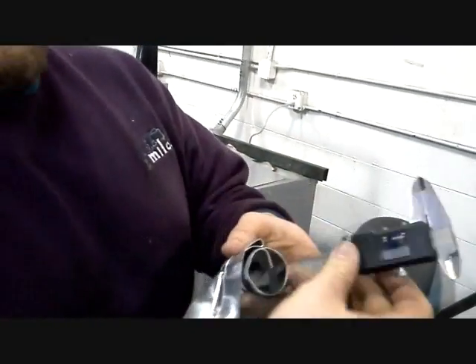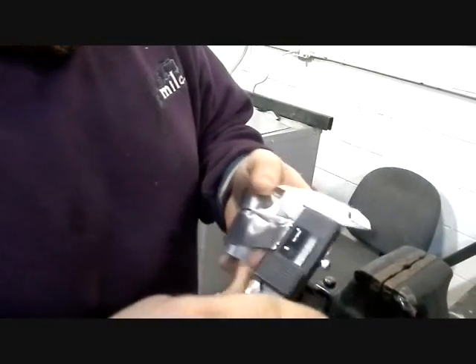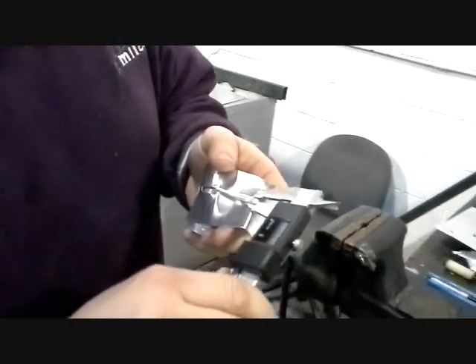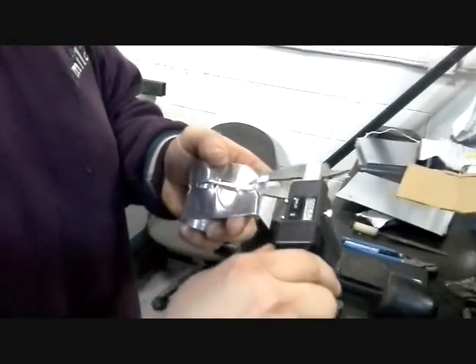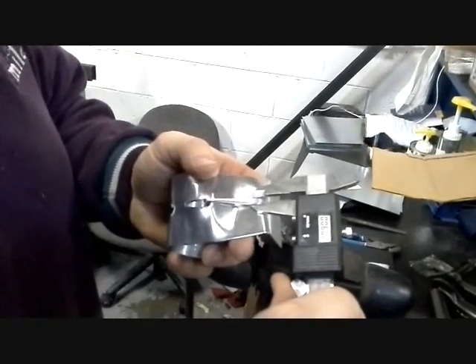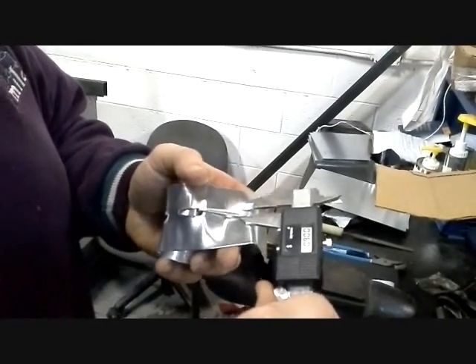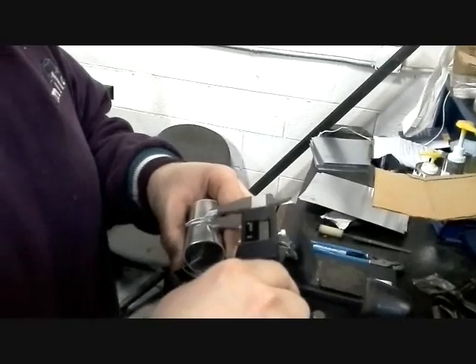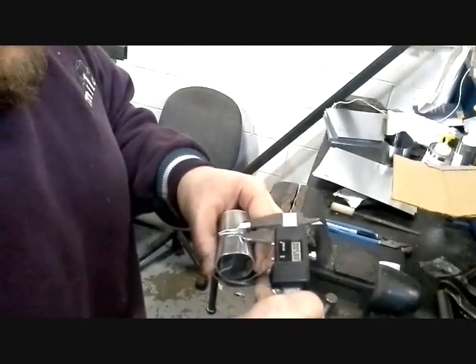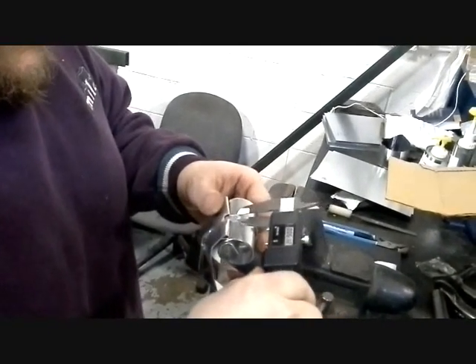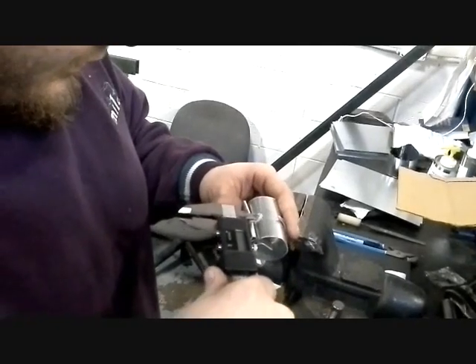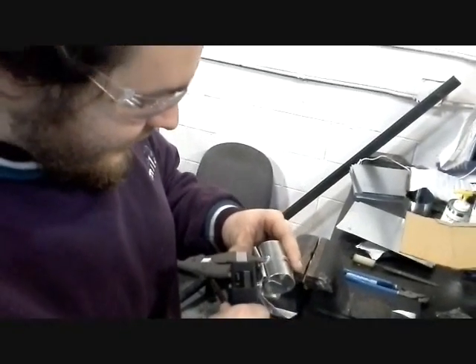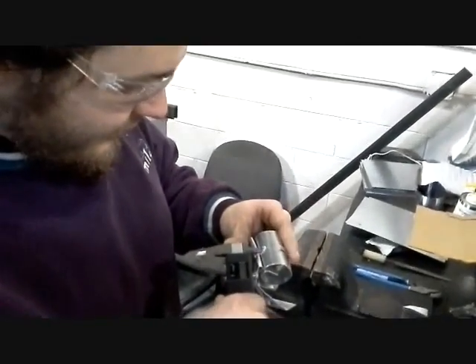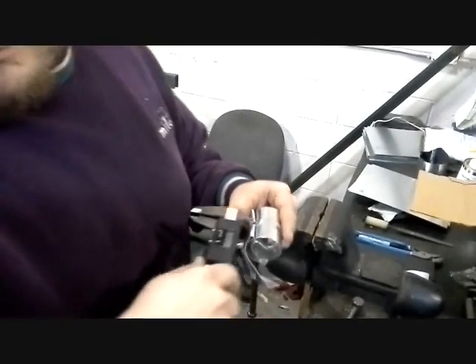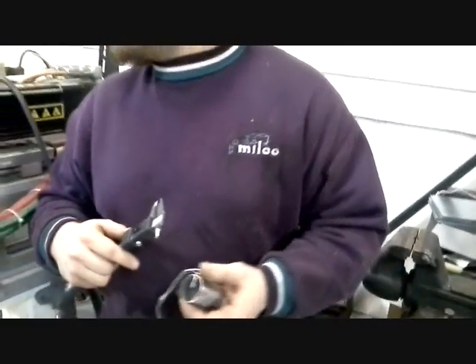And you know it's a good weld when it's tearing away the base material with it, instead of splitting the actual weld. First weld, 6.01. Second weld, 5.88. And your third weld, 6.03. So you're right where you want to be.